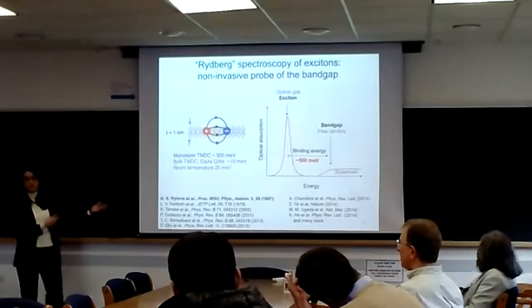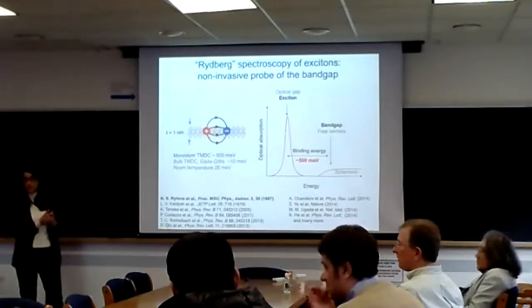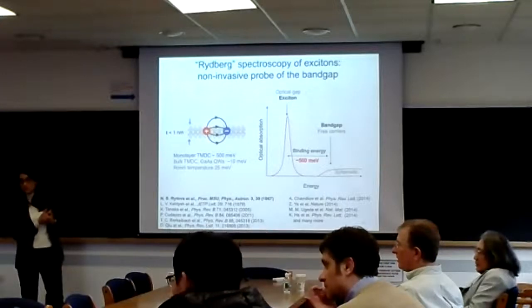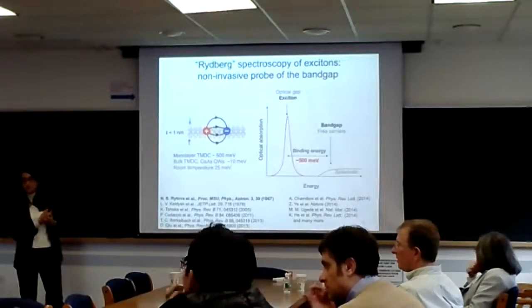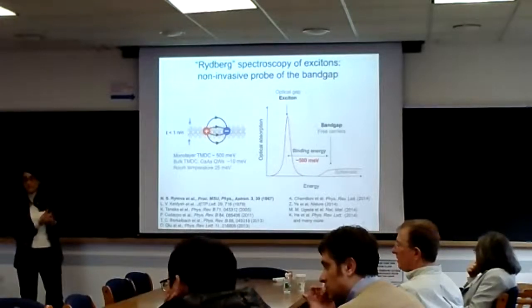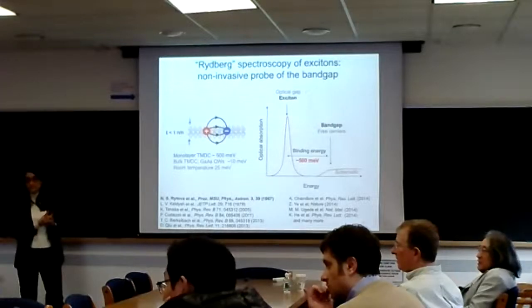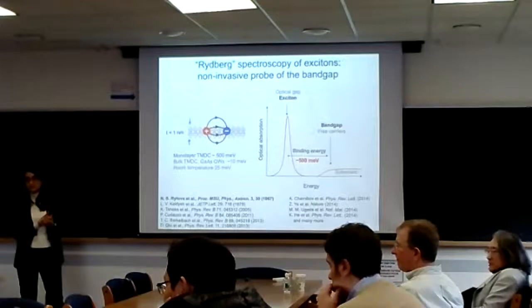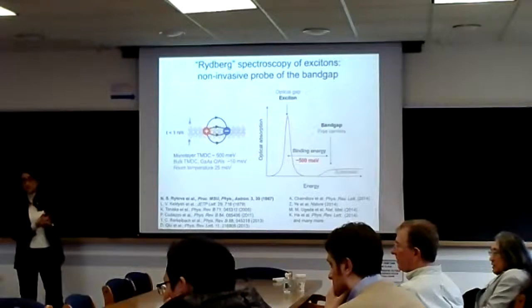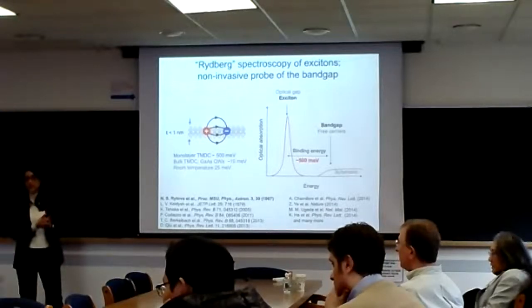You use the Keldysh-Rytova. No. Keldysh basically tells you that at short distances the interaction is logarithmic instead of the Coulomb interaction. Right. But there is a kinetic energy part, and for this you are still using gradient squared. Okay. Despite the fact that the kinetic energy is already a very substantial part of the width of the gap. Right. Okay, which basically means that the exciton radius is a few lattice constants, right? Yeah, it's a nanometer. All right.